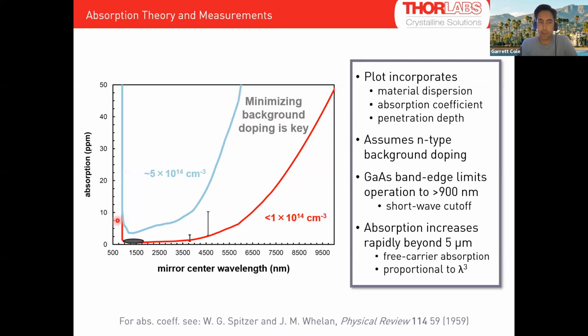So here's two theoretical plots for absorption as a function of mirror center wavelength. I'm going to interpolate a bunch of different Bragg mirror designs to make this curve. And you can see if I bring my background doping in the crystal down from something in the 10^14 level to high 10^13 per cubic centimeter, I can start to push these ultra low level, like ppm levels of losses out to very long wavelengths, sub 50 ppm, out to almost 10 microns. And it's very challenging to bring down the background doping in these semiconductors, but we're making rapid progress.